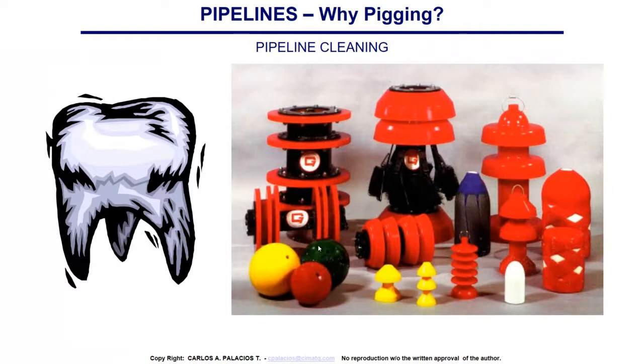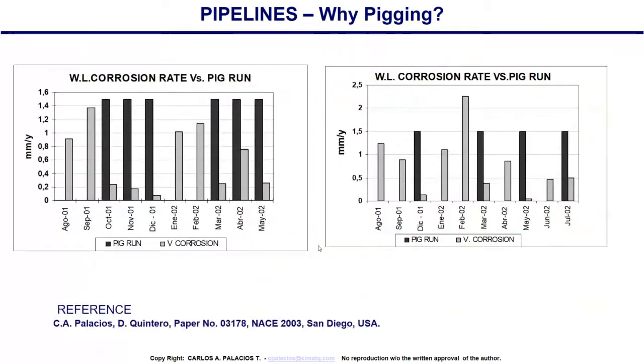Okay? Pigging doesn't necessarily mean that you are removing a corrosion inhibitor. They would not. But normally we increase the corrosion inhibitor. Here is an example of why pigging. Every one of these dark bars is a pigging. Here is without pigging: high corrosion rate. Started pigging: low corrosion rate, low corrosion rate, low corrosion rate. They didn't pig this one: high corrosion rate. So pigging works to reduce the corrosion rate.